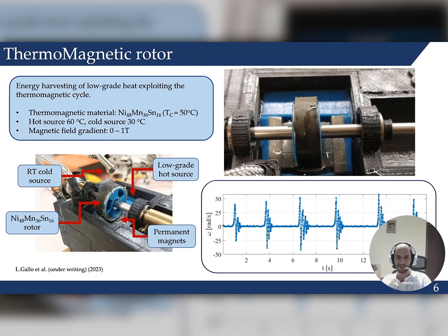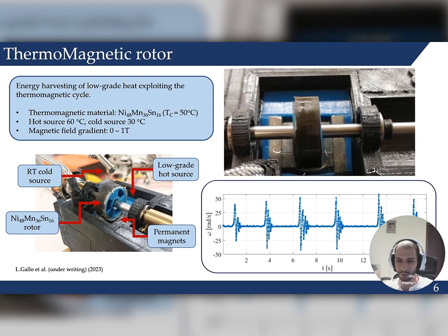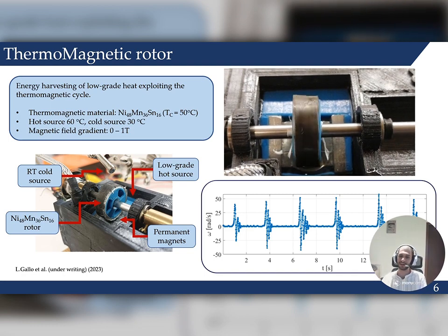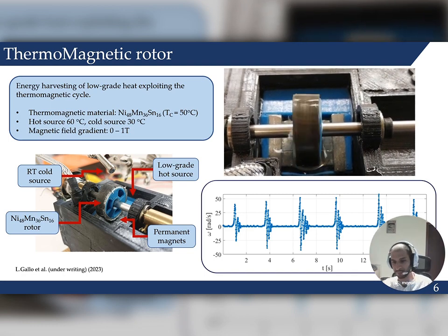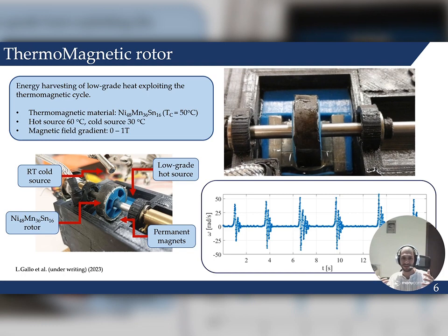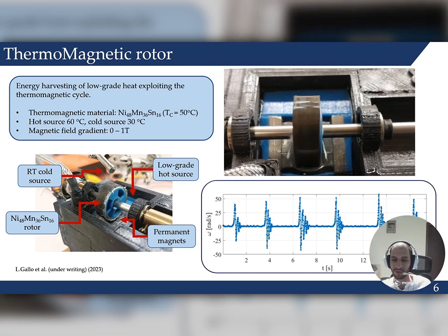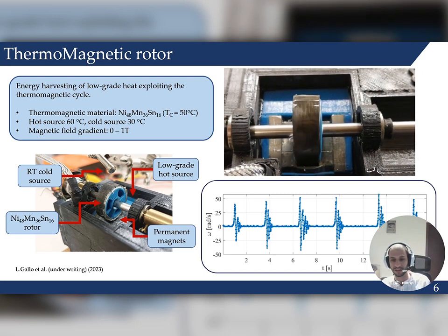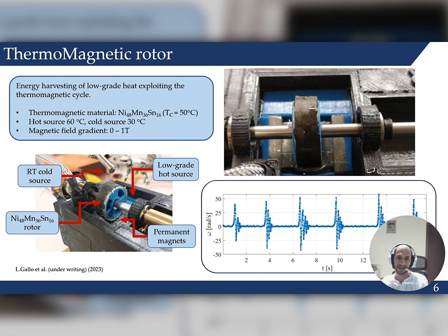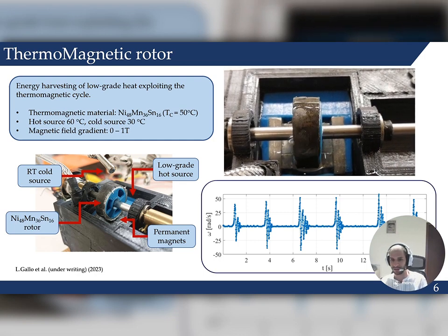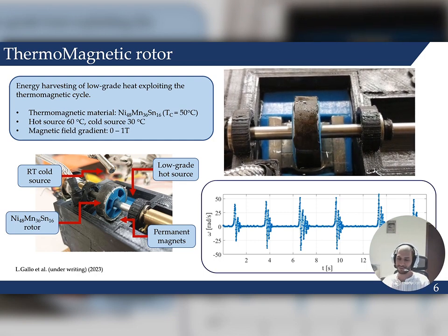And let's move directly to the test of one of our materials. The composition we chose is nickel 48, manganese 36, tin 16. That probably means nothing for you, but you have to know that this kind of composition presents a second order Curie transition exactly at 50 Celsius degrees. Firstly, we reduced the compound to powder, and we made a composite based on epoxy resin and graphene. We added some graphene to increase the thermal properties of the composite.